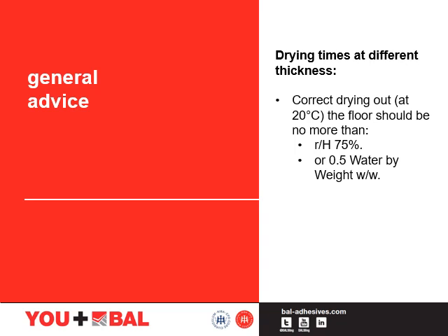by weight scale. We use the carbide method for testing. This is an on-site test that measures the moisture within about 15 minutes. It is, however, a destructive test, so perhaps the use of this on an underfloor heated screed might not be the best option. Forced drying the screed might also be possible. You'd need to ventilate the room and apply external heat or use industrial dehumidifiers.